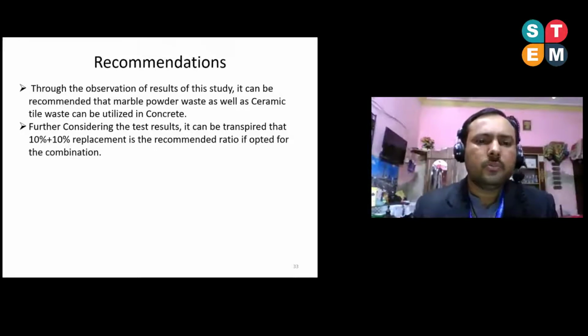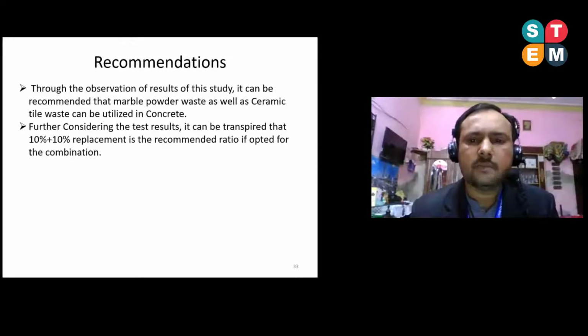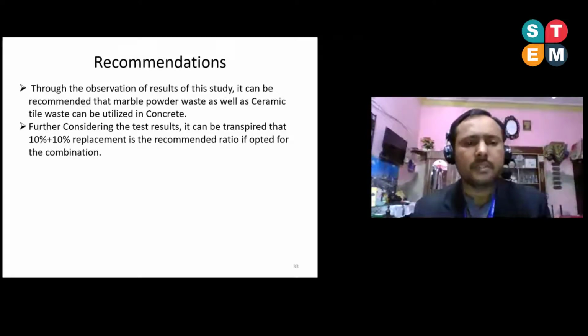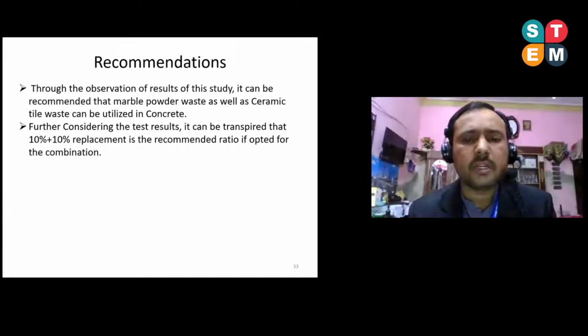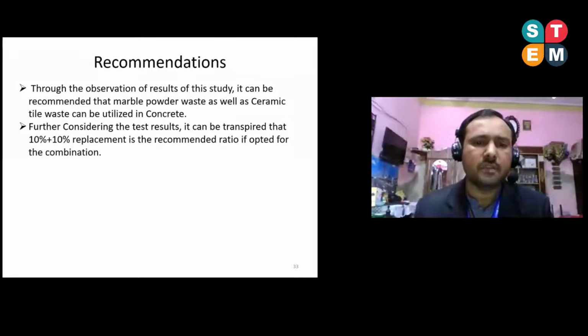Through the experimental observations, or based on the results, this study recommended that the marble powder waste as well as ceramic tile waste can be utilized in concrete. Furthermore, considering the best results, it can be recommended that the 10 plus 10, means the 10% marble powder and 10% ceramic tile replacement, is the recommended ratio for the combination.